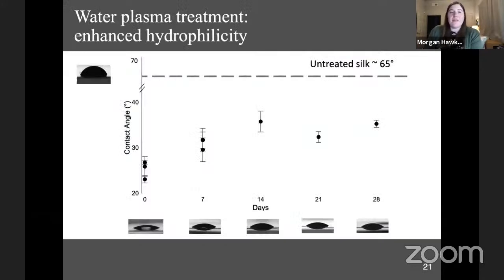So here are some data from my student's preliminary study. On the y-axis, we're looking at the contact angle of the material, and on the x-axis, we're looking at the aging time. So we have here freshly water plasma treated surface, and you'll see the untreated silk has a contact angle around 65 degrees. When it's plasma treated, we observed this dramatic decrease in hydrophobicity. The surface is becoming more hydrophilic.